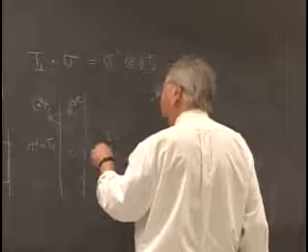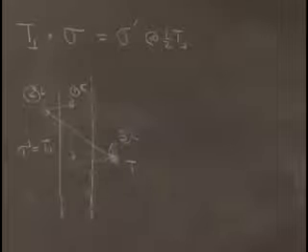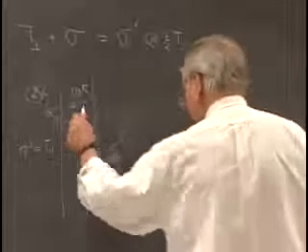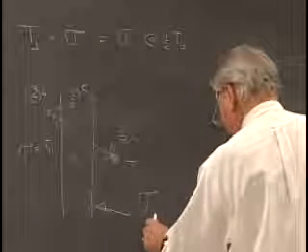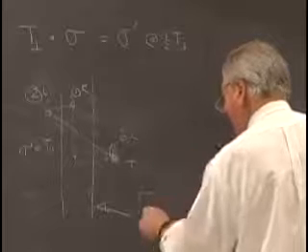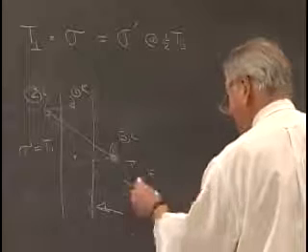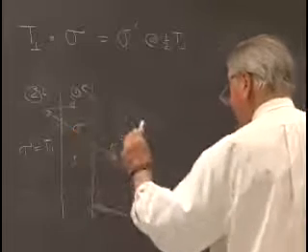Doesn't matter in what order we do them, we get to the same location if we reflect first and then slide, or slide first and then reflect. So this was a new operation that I'll represent by sigma tau. Looks sort of like a symbol for reflection, but the subscript reminds us you've got to translate by an amount tau that is parallel to the initial mirror plane.